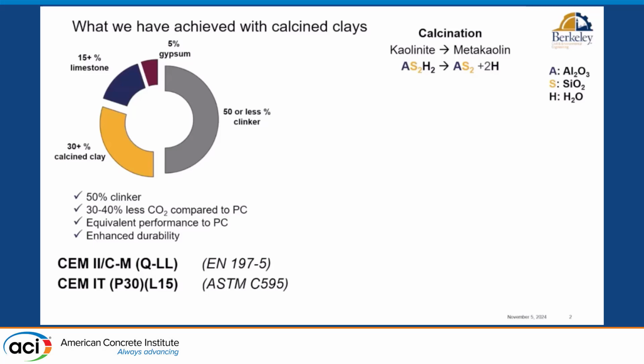And among the advantages of this cement is that we have 50% clinker, or actually less. Some of the work that we are doing right now is to look at what happens and how much further below 50% we can go with the clinker content. And we can save between 30 to 40% of the CO2 by doing so, depending on the technology that you use to calcine the clay, because that's, of course, not a carbon neutral process on its own.